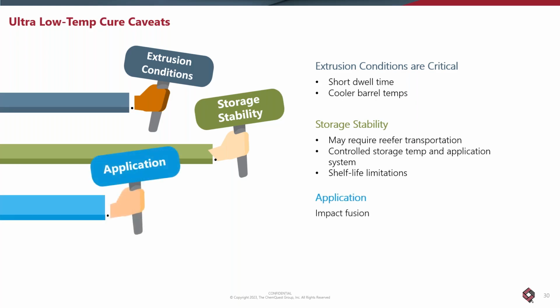Application, and again, this is where we're driving down the melt behavior of these powder particles. And we have an issue depending on how your application system is designed. We're propelling a powder air mixture through tubes and a spray apparatus, which has a certain velocity of the particles. And if you're not careful, if the temperature gets a little too high, you can get impact fusion on the inside of the application equipment, which is definitely a problem.